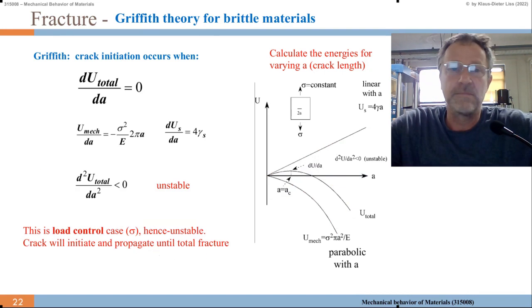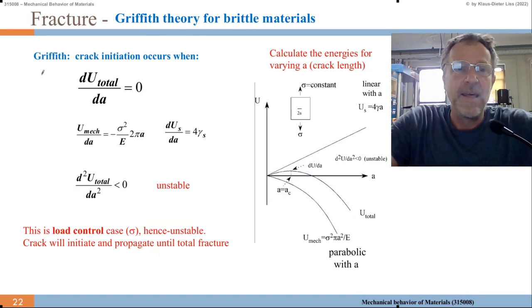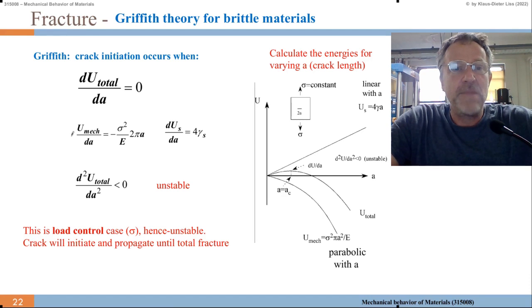So the crack initiation occurs again when dU over dA is 0. And we have dU mechanical over dA, which should be minus sigma squared over E times 2 pi A, and the dU surface over dA equals 4 gamma S.